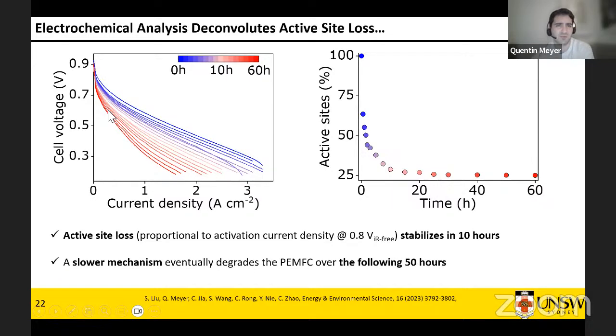So first step, we did some polarization curves, and then we can basically correlate the active site retention or active site loss, which is proportional to the current density around 0.8 volt after ohmic correction. This is what we get. So very clear graph. At the beginning, we have 100% of active sites that are usable, and within 10 hours, we drop to 25%. This corresponds from here to here.